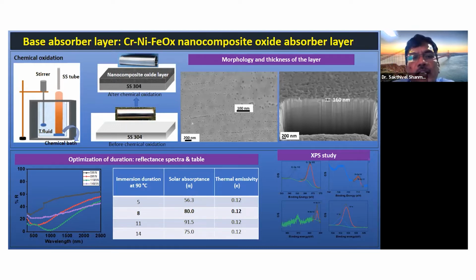So here you can see the best layer. What we observed is that a 160 nanometer layer gives very good optical absorption as well as good stability. After developing this layer, we studied it by XPS analysis, and we observed that all the metal components are converted to metal oxide. So we can see the oxygen peak corresponding to all the metals. We can easily identify this by XPS measurement, and the maximum absorption we observed is 91.5%, but that shows very poor mechanical stability as well as thermal stability.